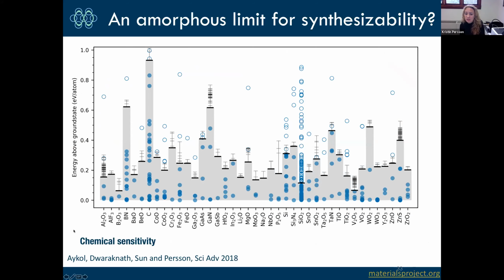Over 44 systems with different stoichiometries spanning oxides, nitrides, different elements, we calculated or approximated the enthalpy of the amorphous state. And we then put that on a graph, and we plotted the enthalpy of all the polymorphs in the Materials Project and the ICSD that have been made under those stoichiometries, as well as the ones that either have never been made or have been made at high pressure or some other conditions. And when you bring them down to room temperature and normal pressure, which is what we're doing the analysis under, they amorphosize or decompose. And we're seeing a remarkable agreement between the amorphous limit, the synthesizability limit, and what can be made or survives under our conditions.